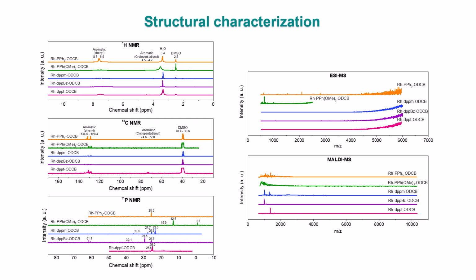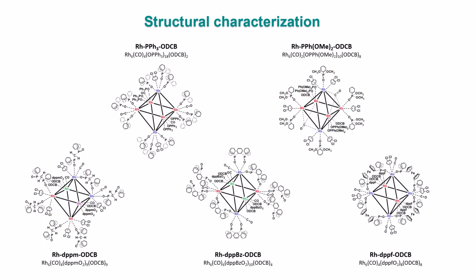The molecular structures were further investigated using proton, carbon-13, and phosphorus-31 NMR spectroscopy, together with ESI and MALDI mass spectrometry. These complementary techniques provided strong evidence for the composition of each synthesized rhodium cluster. Based on all the structural characterization results, molecular compositions were proposed for the five catalysts. Although the phosphine ligands differ, all materials preserve the rhodium carbonyl cluster framework while exhibiting distinct coordination environments that are expected to influence their catalytic behavior.